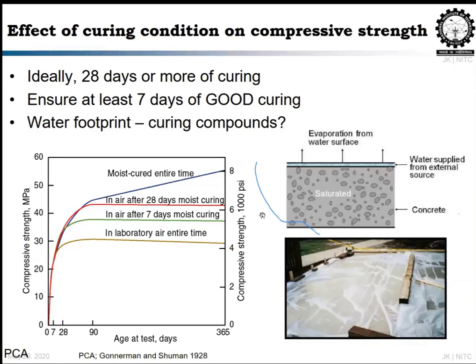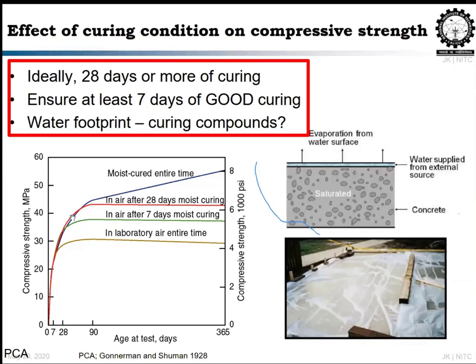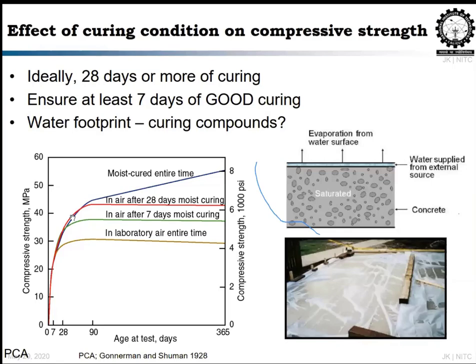But if you see the variation in the strength after almost 60 days, you can see a major difference in the strength. So what is emphasized is at least you cure for 28 days, and if you are using any secondary cementitious materials or fly ash or anything, make sure you are curing for 28 days or more if possible, so that you will get a very high strength, rather than putting a lot of OPC thinking that OPC will give you strength. It will give you strength obviously, but you can save money just by using fly ash and proper curing. So that is a very important takeaway.